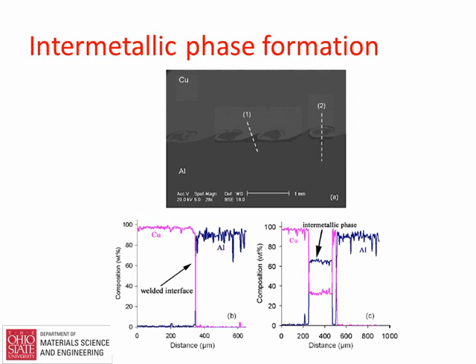However, if these intermetallics are not continuous, it's a good thing, because even if they are brittle, if there is a ductile phase in between, those brittle phases would not affect it that badly. If there was a more or less continuous brittle phase between the pair, then you can imagine a crack could traverse through the interface and cause failure. So I think this weld is good, but we'll see some examples of bad welds at a later stage.